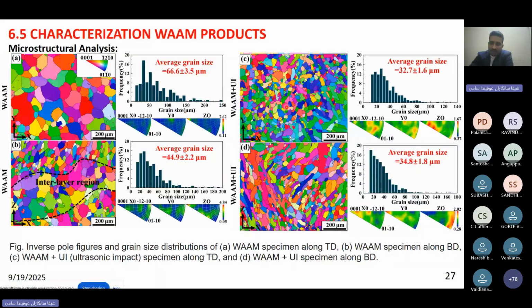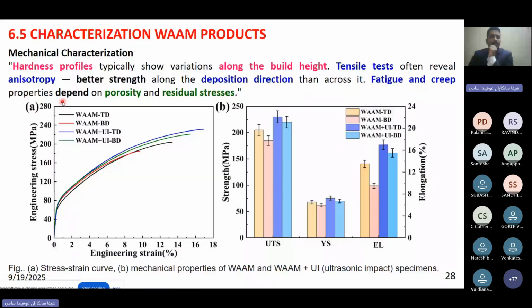Whenever we have a fine grain structure, obviously we can have very good mechanical strength. You can see these are the inverse pole figure images, and these are the corresponding grain size distributions. You can see how the grains are shifted towards the low angle. More grains, more frequency, shifted in lower angle. Therefore, this sample will give you more strength compared to this one, because it has a coarse grain structure. This is the way we have to do the characterizations once we build the component through the WAAM technique. Okay, right. And yes, this is mechanical characterization.